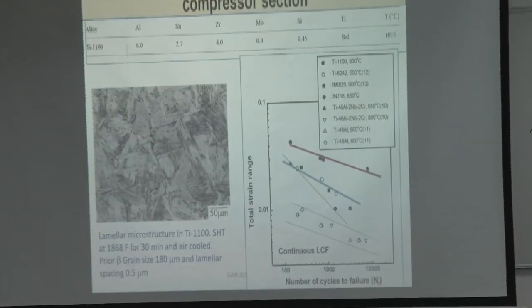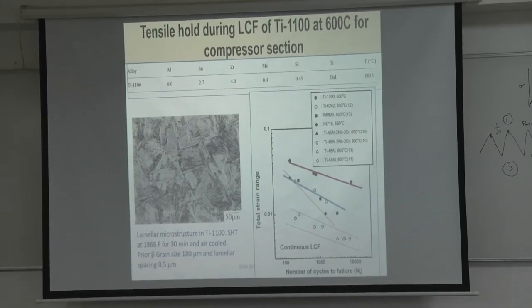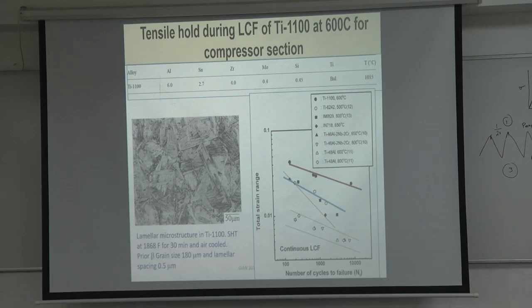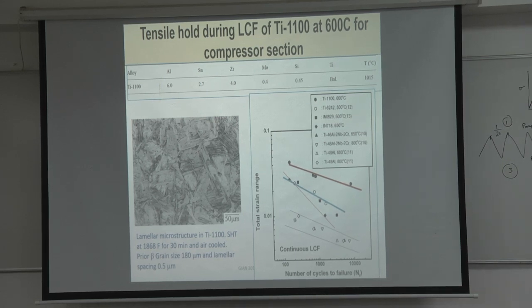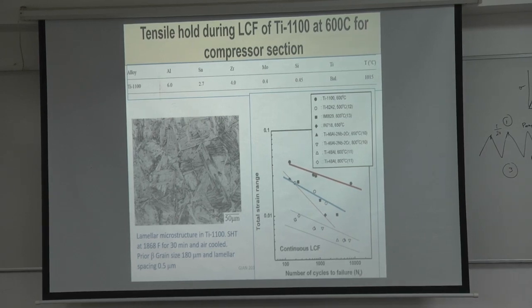Lamellar microstructure. Can somebody tell me why this lamellar structure looks so different from a normal lamellar microstructure? Bhanumati, you should know that, right? You have an answer? It looks a little bit different, but it is a lamellar structure in 1100. Solution heated at 1868 for 30 minutes, air cooled. There is a prior beta grain size, and there is the lamellar spacing.